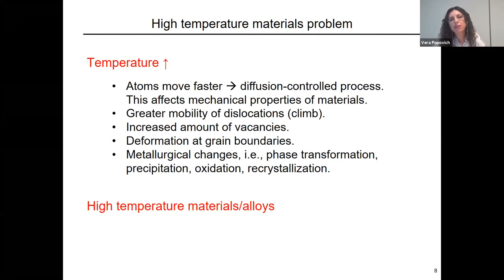So when we look into materials, we for sure like to look into the movements of atoms or dislocations. When the temperature increases, atoms start moving faster. That's why we also say that high temperature creep, for example, is a diffusion controlled process. And this definitely affects mechanical properties. So we have a greater mobility of dislocations, an increased amount of vacancies that are formed, and we have deformation along the grain boundaries. In creep, and we will look into creep mechanisms, quite often you look into deformation along the grain boundaries.